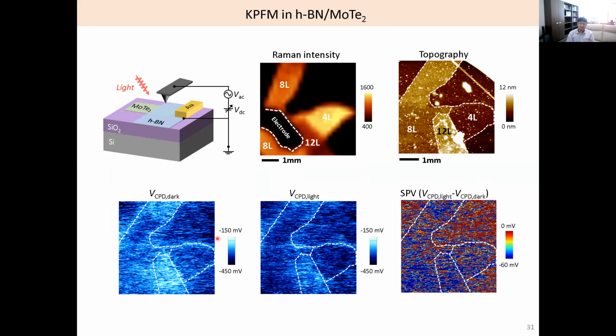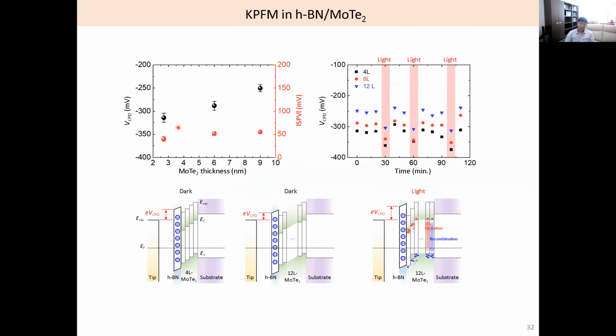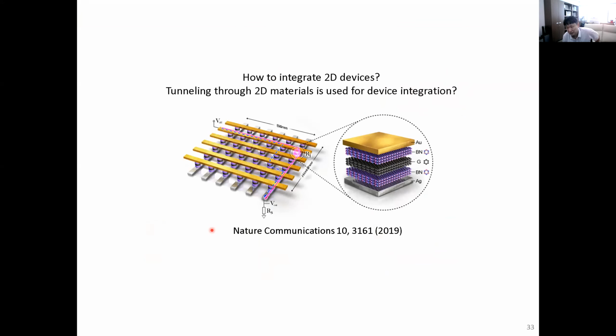So as I said, my expertise is somehow related to STM and KPFM. KPFM is Kelvin probe force microscopy. So we measure the surface potential in the dark state and bright state, and we measure, for example, the work function of 2D materials. For example, in the dark state, 4-layer and 12-layer samples have different surface potentials or different work functions. It is simple: it is because the depletion width is longer than the thickness of the 2D materials. So within the depletion width, if we change the 2D material thickness, we have different band bending. And we could understand our device performance. Okay, that was the first part.